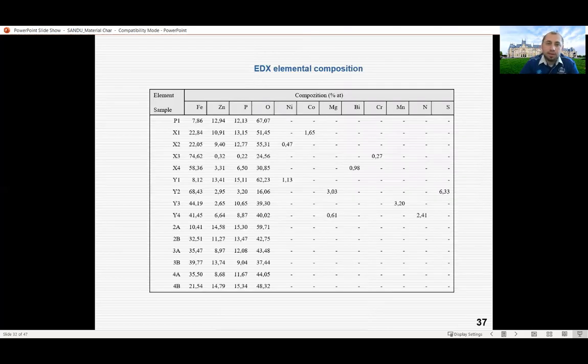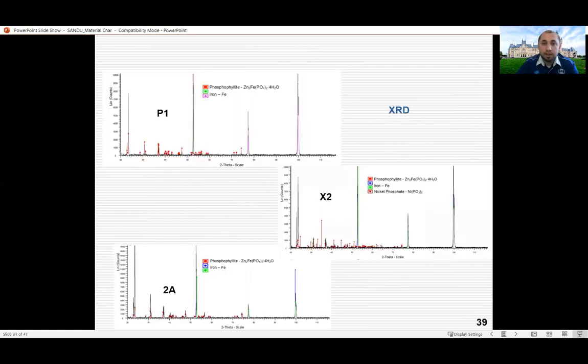And a soldering alloy, you can see here in the down part, that's a soldering alloy. It's their structure on the scanning electron microscope. This is how we get results from the EDX on various types of composition. For example, here I had like 16 samples obtained and made analysis for all of them. Some of them had nickel, some of them had cobalt, magnesium, bismuth, chrome, manganese, and so on, depending on the layer obtained. So we can have here the elemental composition for this, but the EDX allows us to get mass percent or the elemental composition, depending on what we require for our study.